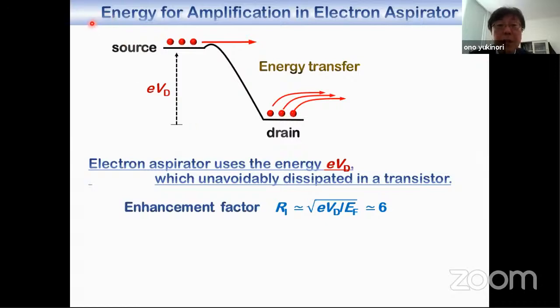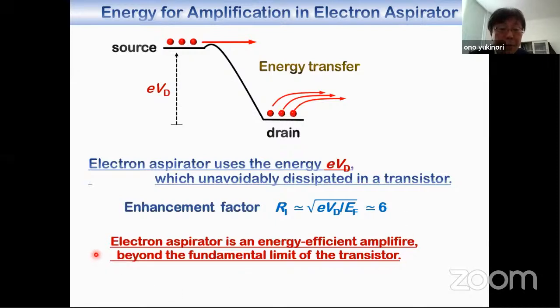On the other hand, in the electron aspirator, the energy gained from the electric field can be transferred to the other electrons before it is dissipated to the phonon bath, which means that the electron aspirator can use the energy eVD, which is otherwise unavoidably dissipated in a transistor. So in this case, the enhancement factor is given by this simple equation, the square root of eVD divided by the Fermi energy, which comes to about 6 in this experimental condition. And as I explained, the experimental data shows that the maximum enhancement factor was about 3. So this means that we still have some room for improvement of the device performance. But in summary, the electron aspirator is an energy efficient amplifier beyond the fundamental limit of the transistor.